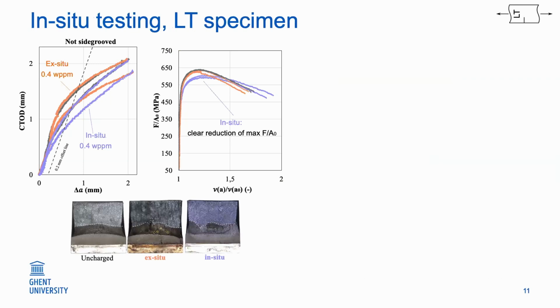Then for in situ testing, still LT, there's a big change. You can see it on the right specimen here, and that there's almost no microvoid coalescence left. But actually, the resistance curve looks not that bad. I think if you would average it, it's a reduction of 24%. But if you look at the normalized scores, it is quite a reduction.